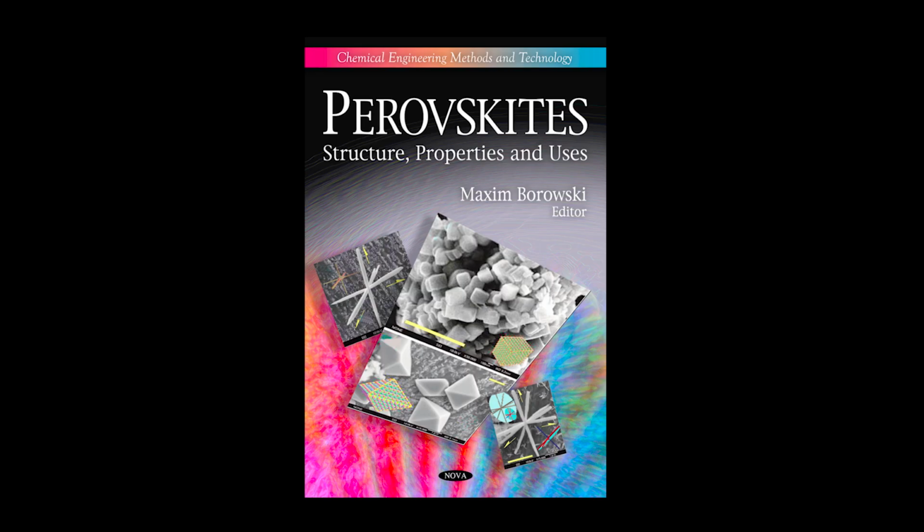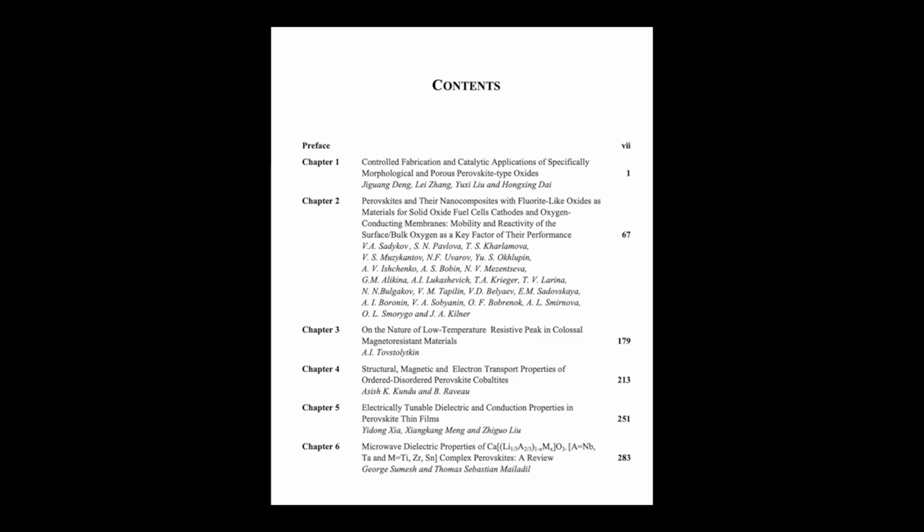Yeah. That's exactly right. Oxygen transport in these perovskites is entirely dictated by the concentration, usually denoted by delta in the formula like ABO3-delta, and the mobility of those oxygen vacancies, which we often write as V_O with two dots, to show their effective positive charge. Critically, the concentration of these vacancies in doped perovskites like lanthanum strontium cobaltite, La1-xSrxCoO3, isn't fixed. It's not just set by the doping level, it's a dynamic thermodynamic property. It's highly sensitive to temperature, and maybe most importantly, it depends strongly on the external oxygen partial pressure, PO2, the concentration of oxygen gas surrounding the material.